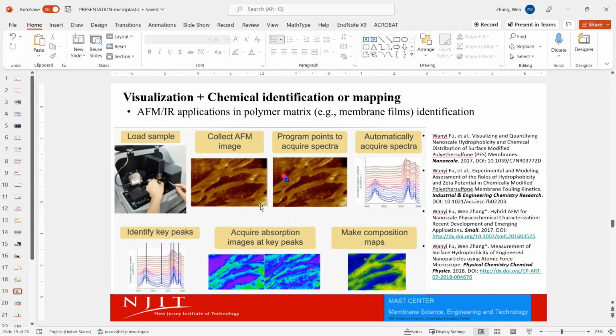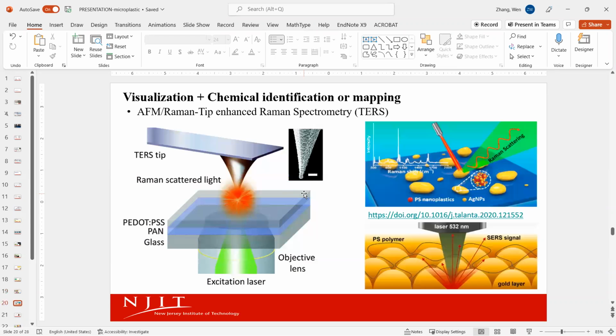So coming back to the plastic particles, we can certainly rely on the same principle and generate information on plastic particle morphology as well as their chemical information, especially when the plastic particles have chemical changes, chemical degradation. Then you need a tool to accurately describe their surface states. Similarly, besides AFM and IR, we can certainly combine the use of AFM and Raman. Actually, this is even more advantageous because you probably heard about tip-enhanced Raman spectrometry, right?